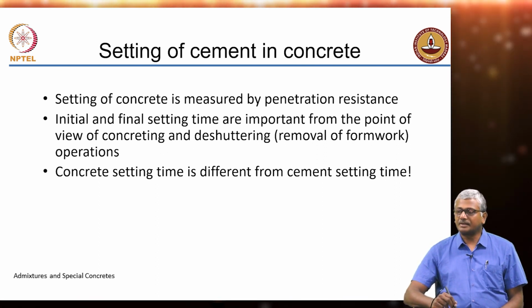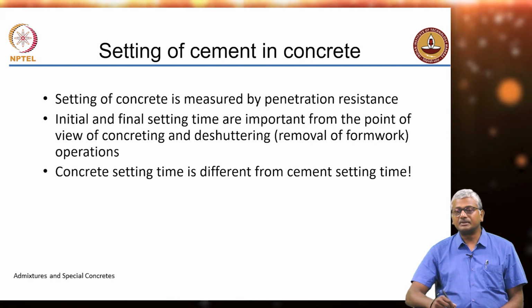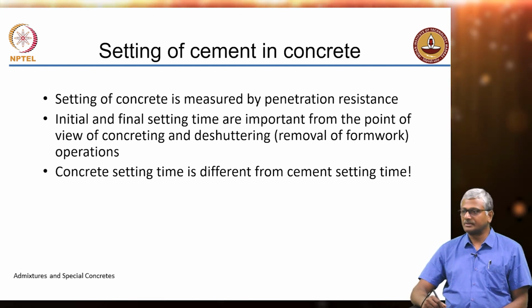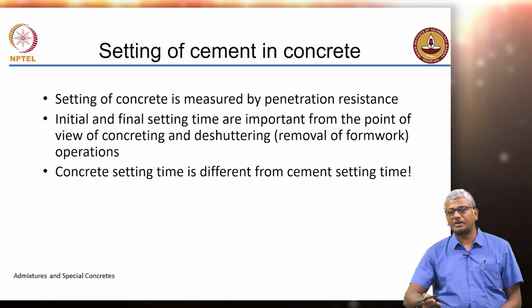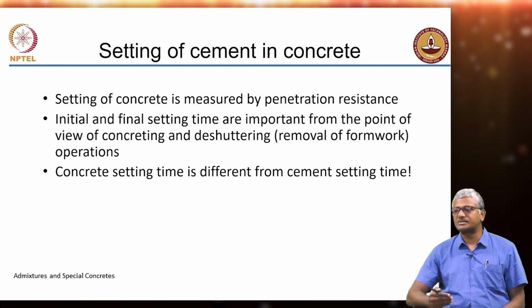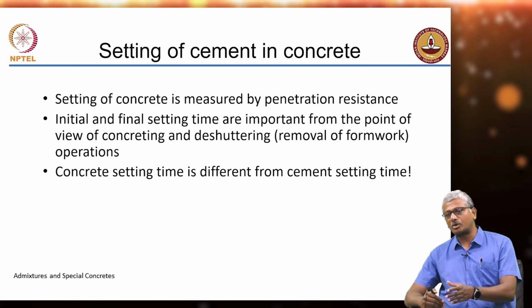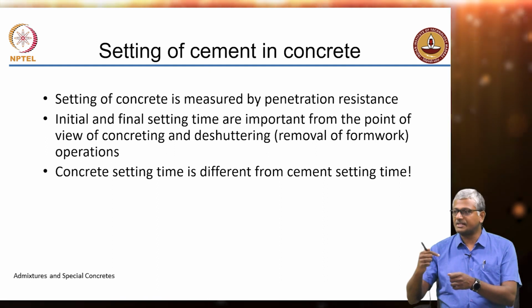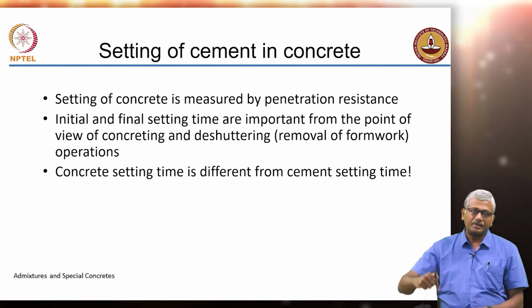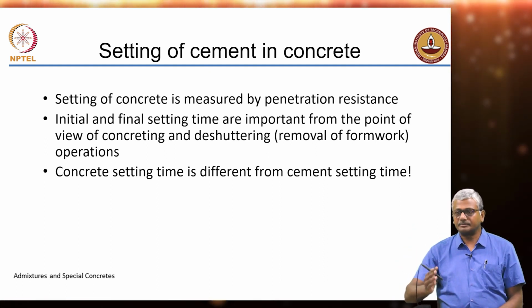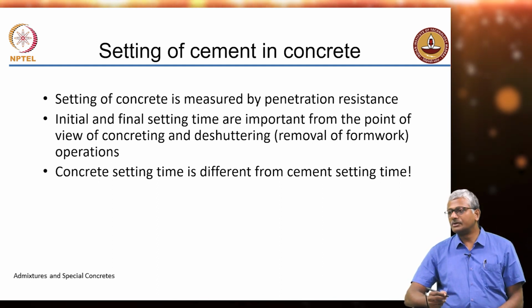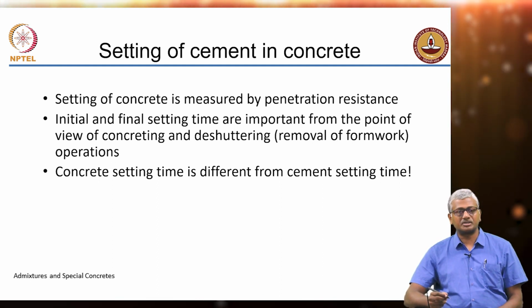and because of that you need to start measuring the concrete setting time, which can be done quite easily with the help of a penetration resistance device. So, you take fresh concrete that is supplied to the field, sieve it through a 4.75 mm sieve, extract the mortar component out, and just have these penetration needles that are actually inserted into the concrete at different time intervals to see the resistance to penetration of the concrete.